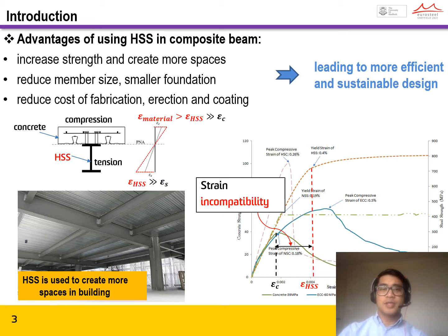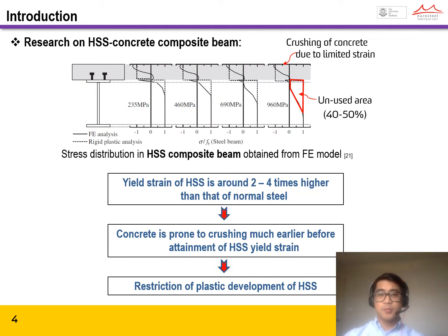But when high-strength steel is used, the much higher strength of high-strength steel compared to concrete leads to strength incompatibility between them. Some research has pointed out that a large area of the high-strength steel beam has not been used when working, and the main reason for this is that the concrete slab on top is prone to crushing much earlier than the attainment of high-strength steel yield strength. In other words, it restricts the full development of high-strength steel.